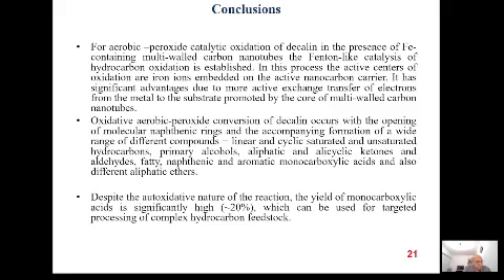Oxidative aerobic peroxide conversion of decalin occurs with the opening of molecular naphthenic rings with concomitant formation of a wide range of different compounds, like linear and cyclic, saturated and unsaturated hydrocarbons, primary alcohols, aliphatic and alicyclic ketones and aldehydes, fatty, naphthenic and aromatic monocarboxylic acids, and also different aliphatic acids. Despite the auto-oxidative nature of the reaction, the yield of carboxylic acids is significantly high, about 20%, which can be used for targeted processing of complex hydrocarbon feedstock.